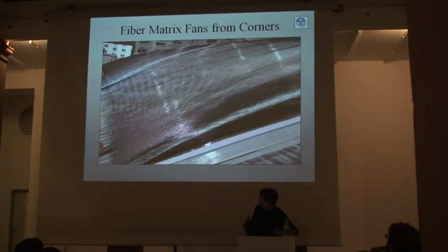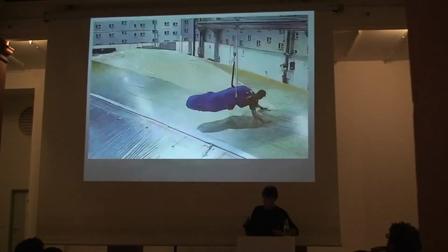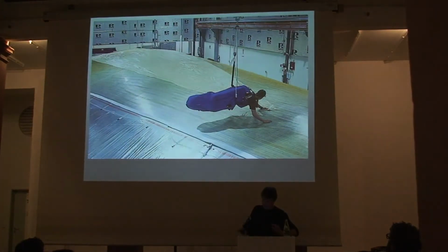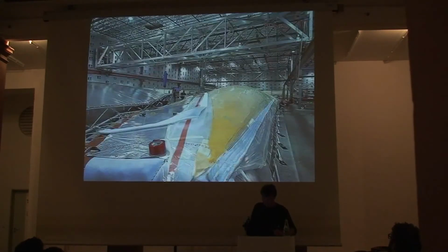And again, as the fiber fans out from the corners with the highest loaded part of the sails, it's the body of the sail. And after the fiber architecture is laid down on the film, we pull 2 more films over the top. This is what you call the mid film. It's got a scrim on it that provides a little bit of tear strength, so a little bit of off-axis load carrying ability in the direction that the fiber doesn't have any strength in. So in the non-orientated direction of the sail.